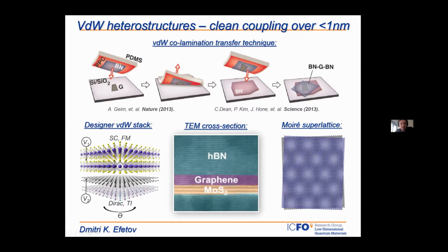So, for example, with hexagonal boron nitride flakes, through the stamping technique, one can pick up graphene layers and repeat this trick many, many times. And one can basically assemble layers on top of layers of two-dimensional materials. And one can basically define the sequence and the orientation at which these layers are deposited on top of one another.